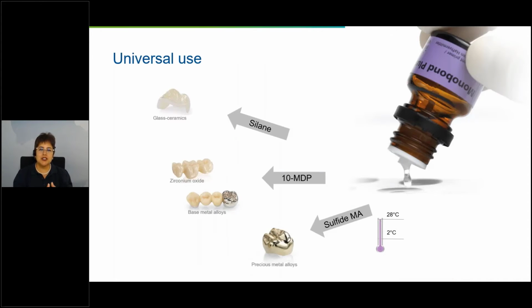For adhesive cementation, I personally preferred Monobond Plus in the past. Monobond Plus is a universal primer which can be stored at room temperature. And it is indicated for glass ceramics, oxide ceramics, metal alloys, and composite. It contains 3 active methacrylic groups: the silane methacrylate, which will react with the glass ceramics; the 10-MDP, which will react with zirconium oxide and with the base metal material; and the sulfide methacrylate, which will react with precious metal.